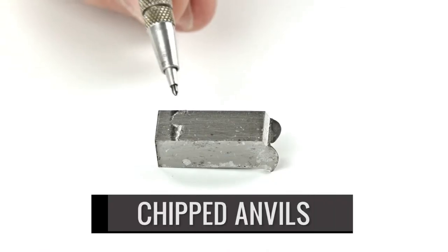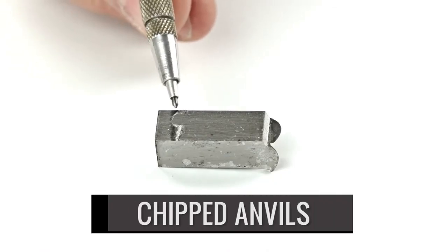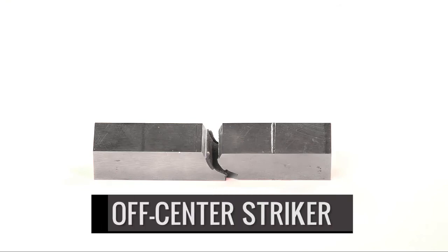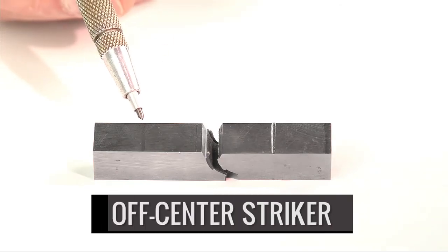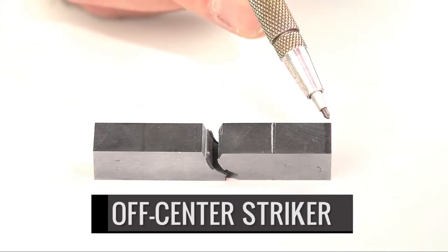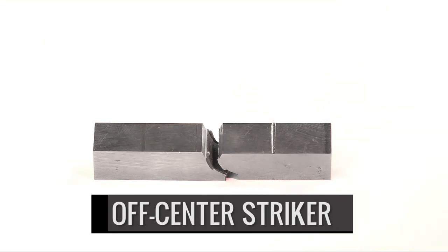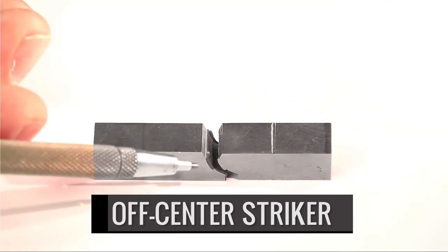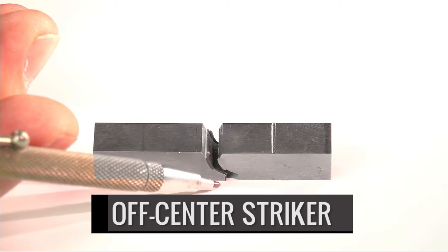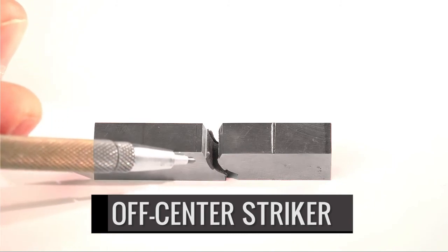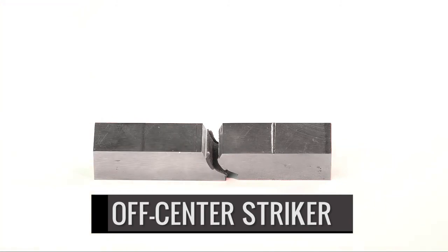Chipped anvils leave distinctive markings. The anvil markings on a specimen that was impacted off-center are offset from one another when the ends of the broken specimens are aligned. And since the specimen is not impacted directly behind the notch, the fracture surface plane is on an angle connecting the notch and the position of the striker on the back of the specimen.